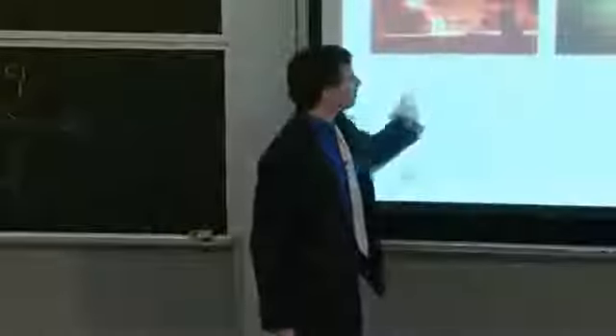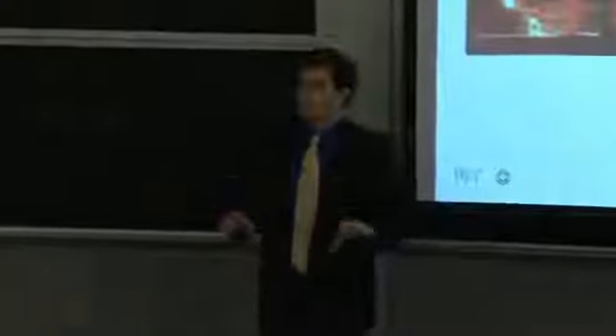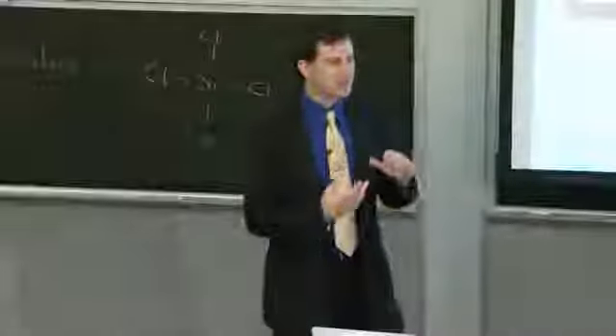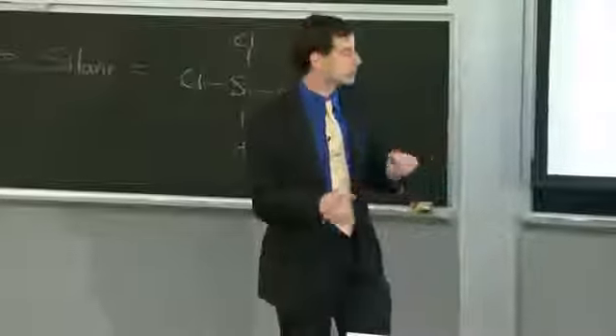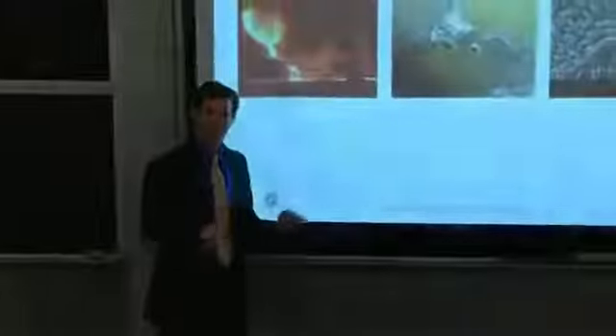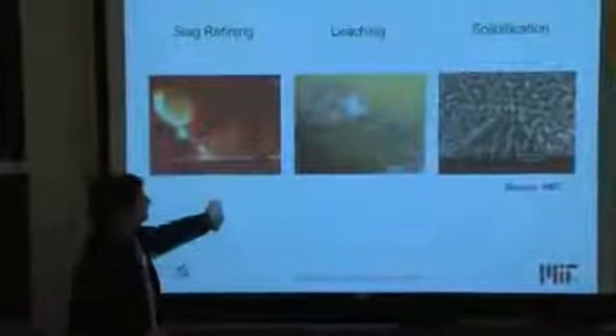And we pour it on top of our silicon, and it's able to absorb, say, the phosphorus or the boron that's inside of our silicon so that we reduce impurity content. And then we can add the phosphorus and boron later intentionally, but to the concentrations we want, not to exuberantly high concentrations that might be found in nature.